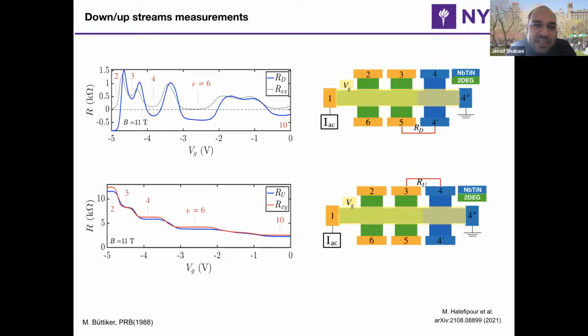So if we basically get trace cuts at 11 Tesla, so I park the magnetic field at 11 Tesla, I measure RXX in the top left that is shown in the black trace. You see that it's a normal looking quantum Hall, right? And I can basically say this is what filling factors these are. And then now, same setup, I just measure now across the interface and I call it RD, the downstream. And now you see blue very happily when it gets to a quantum Hall effect, it dips into a negative resistance, right? So that's kind of surprising, but maybe it still is part of this picture.